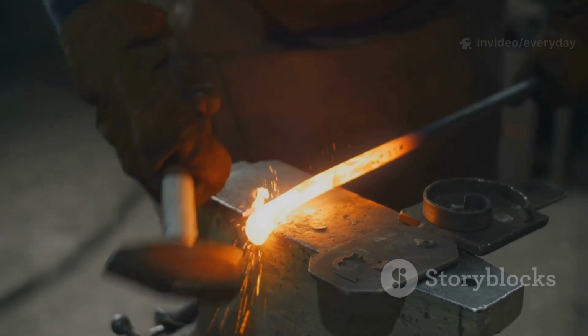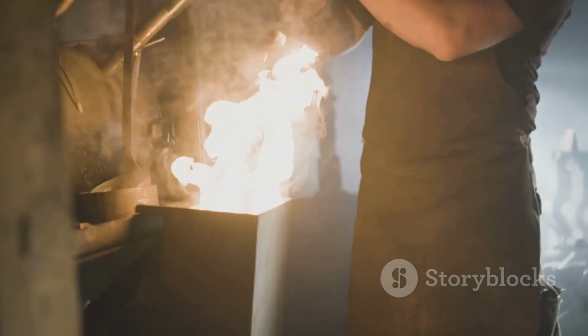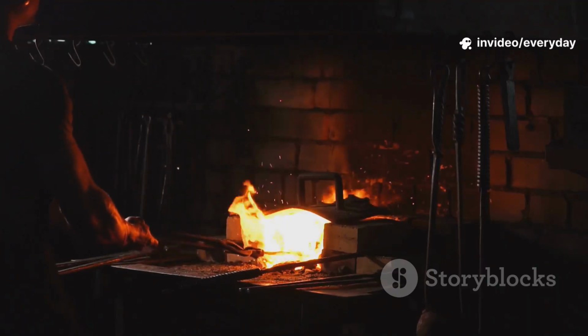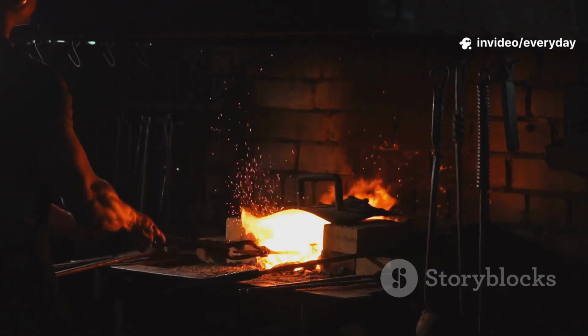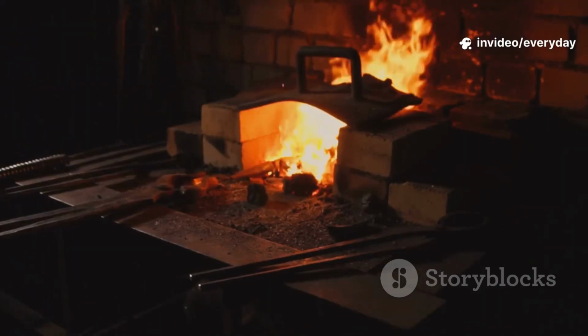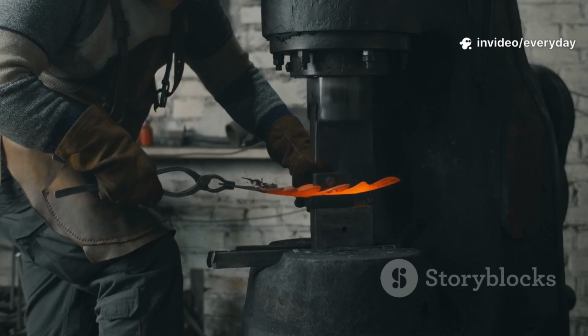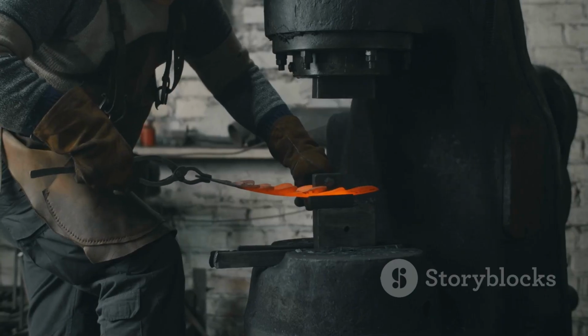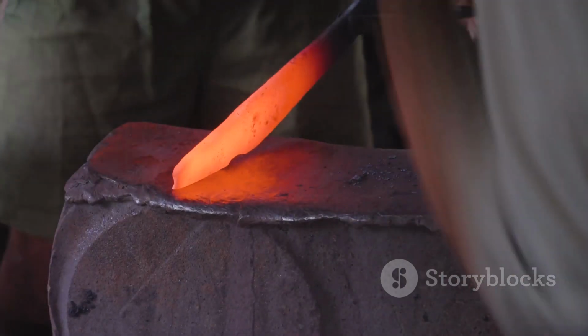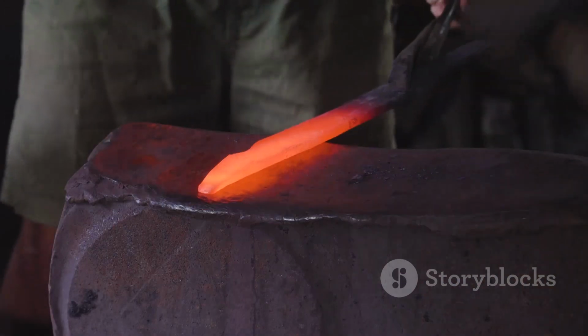At welding heat, move with purpose. Light, rapid blows, end to end, to set the weld. Sparks and expelled flux are good signs. Don't hammer as it cools. Shear risk is highest now. Reheat, reflux if needed, and repeat with slightly firmer blows. Two to three heats typically ensure a solid bond. Then begin to draw out, but only at hot working heat. A good weld is silent and seamless, the quiet reward of precise heat control.